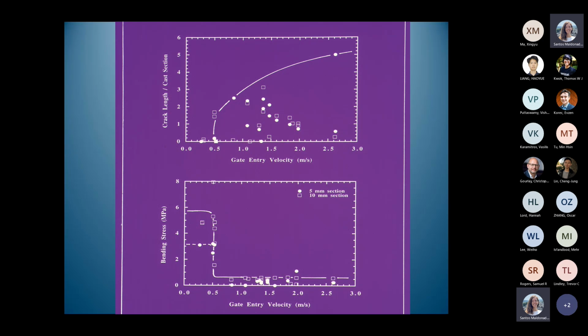But down here, the castings you make are safe, free from cracks. Okay? And then when we looked at the strength, we had good strengths up here, and then a cliff edge here, and then awful strengths along here. And it was this result here, these two castings, that really alarmed me.